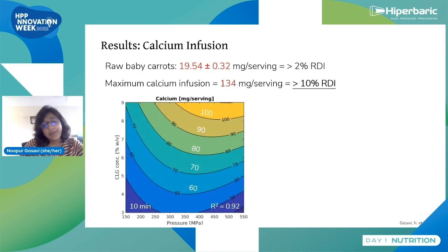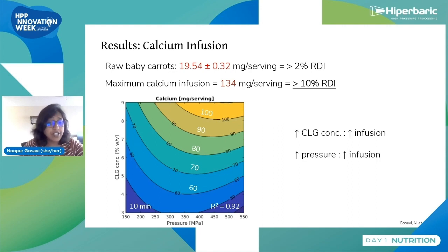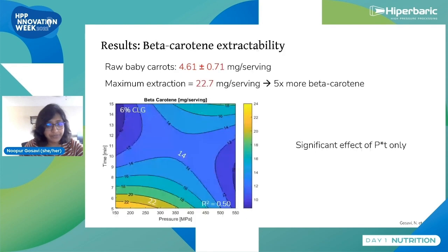So you'll see that the amount of calcium in baby carrots was about 20 milligrams per serving, but high pressure could infuse up to 134 milligrams per serving, which was more than 10% of the daily requirement of calcium. As we increase the calcium solution concentration, the amount of calcium infused increased. As we increase the pressure, the infusion increased. So together, increasing pressure and calcium solution concentration led to higher infusion.